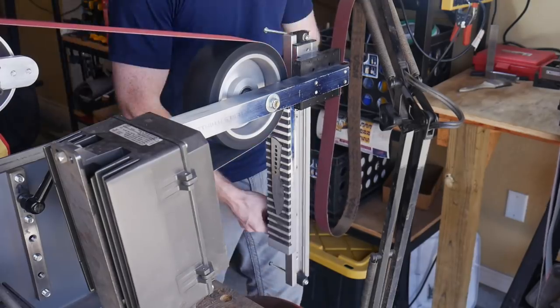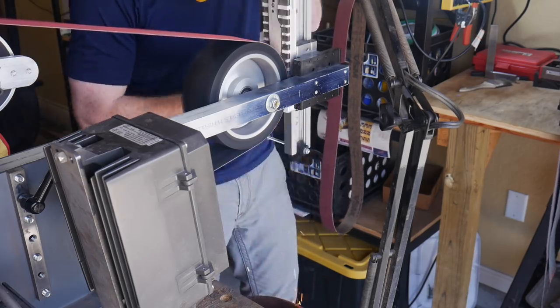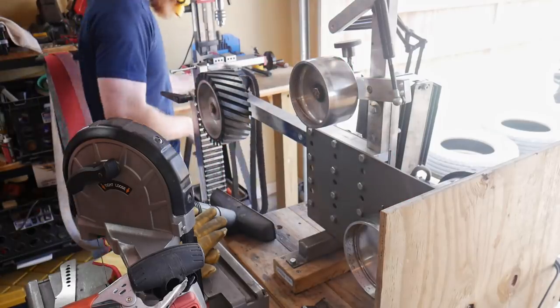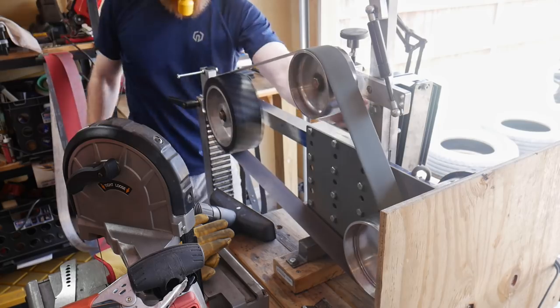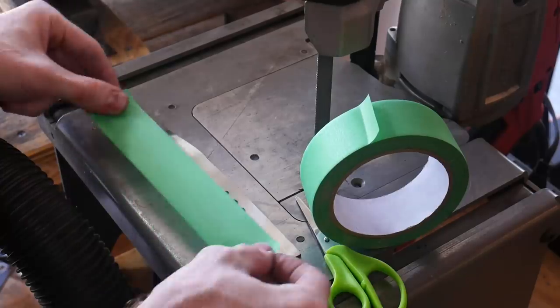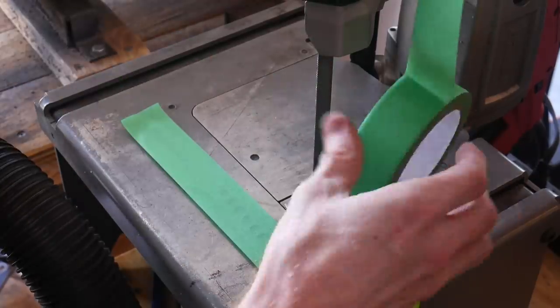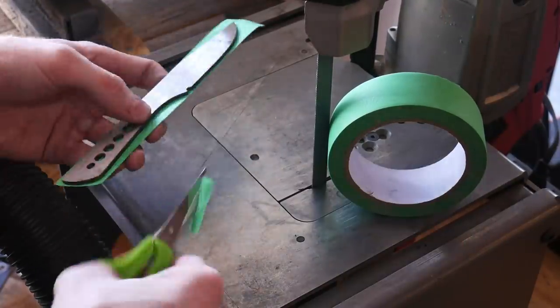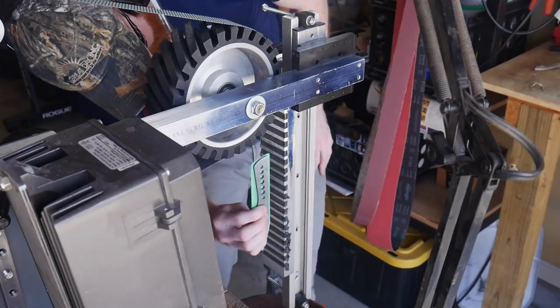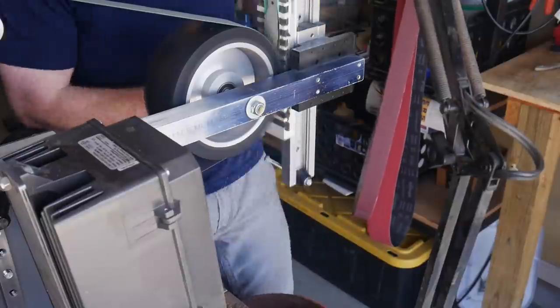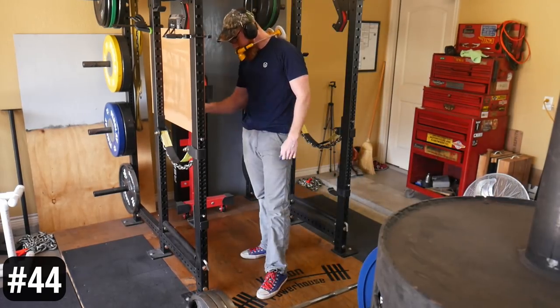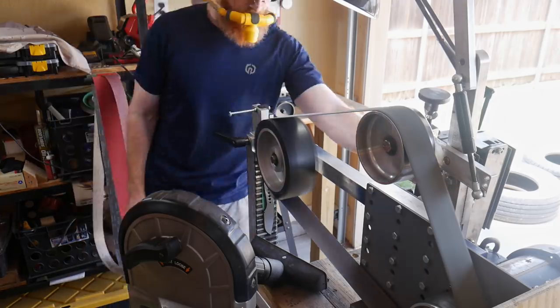We go straight over to the surface grinder and start knocking off any layer of decarb or discoloration on the flats of the knife. I start off with a 120 grit ceramic belt, then I move to a 280 grit gator belt, and then eventually move to a cork belt, a 400 grit cork belt. Once I get one side done, I tape it off and then put the tape side down on the surface grinder to get the other side nice and smooth as well. If you do not tape it, I found that the magnetic chuck will scratch your finish even though it's made out of aluminum.